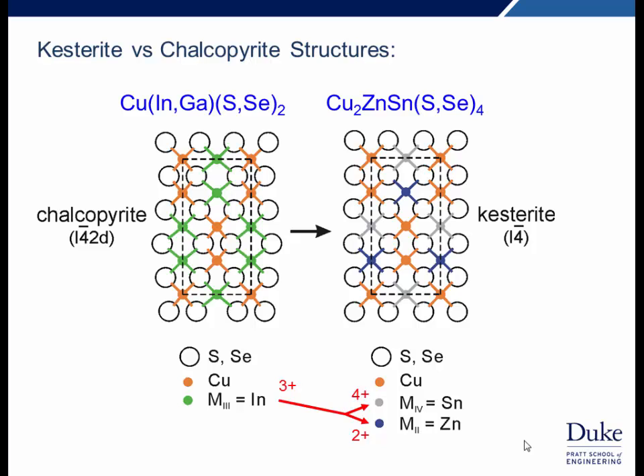For this reason, there's interest in a third chalcogenide technology, CZTS, in which the indium and gallium in CIGS is replaced by the more plentiful and lower cost zinc and tin. In this substitution, we're replacing one trivalent ion by roughly equal numbers or ratios of divalent zinc and tetravalent tin. And because of the ordering of these ions in the tetragonal unit cell, we get a different space group, I4 bar versus I4 bar 2D, and therefore a different structural type known as kesterite.